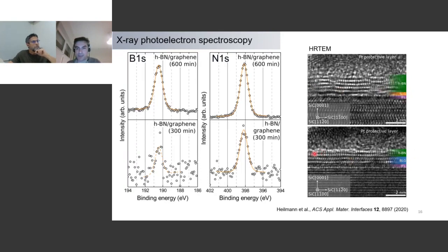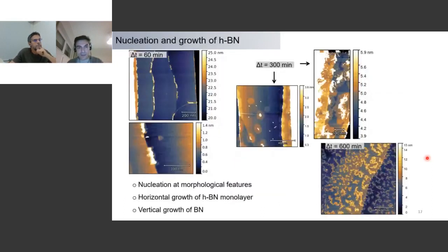And you can see that although the HBN is not perfect, and I'll show you soon why this is the case, we do see a sharp interface forming between the two materials. But what I find nice, and I want to show you here, is how the nucleation takes place. So here I show you growth experiments for different times.